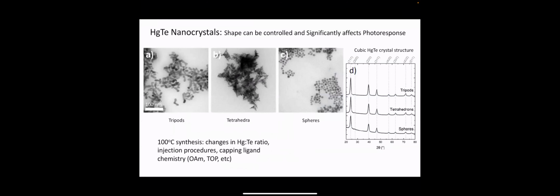The interesting thing about the mercury telluride is that not all the nanocrystal quantum dots are photoconductive. And so that might sound like an obvious thing, but it turns out, at least from what we've found, that the shape of these mercury telluride quantum dots is really important. So spherical mercury telluride quantum dots generally, if they do have a photo response, it's really weak. And in general, even with the ethane dithiol treatment it is not particularly good.